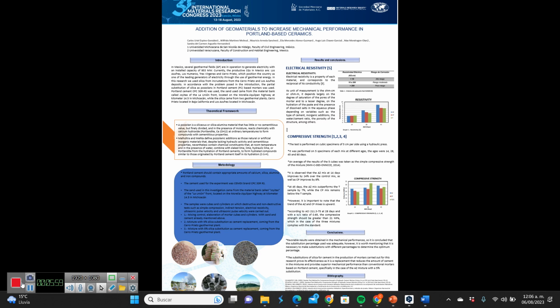Finally, as a conclusion, we can say that favorable results were obtained in the mechanical performance. So the substitution percentage used was adequate. However, it is worth mentioning that it is necessary to make substitutions with different percentages to determine the optimum percentage. We can also say that the substitution of cement by silica in the elaboration of mortars carried out for this research proved their